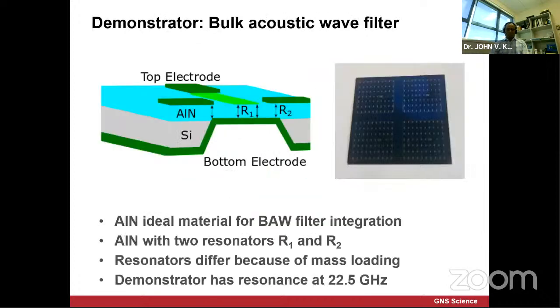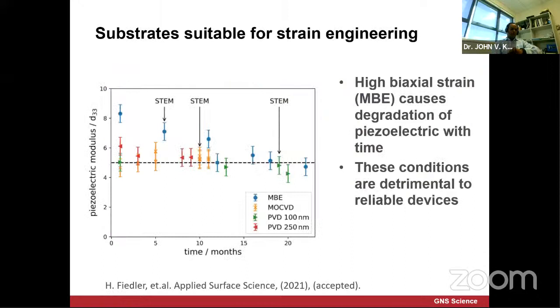So we did look a bit more closely, even if you have various grown films and various conditions, can we really retain the piezoelectric modulus significantly? And how stable is it? Because the strain you're talking about is at interfaces, and interface strain is hard, depending on the surface and the films, how they're grown. So we did a detailed long-term study to identify the degradation at the interface, and amazingly we found that up to a certain time it's stable, then goes down.